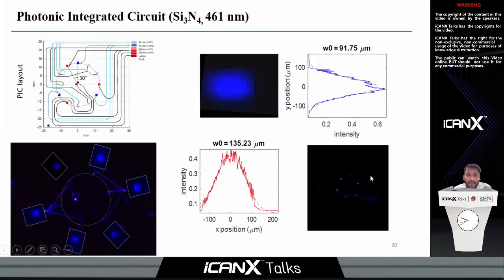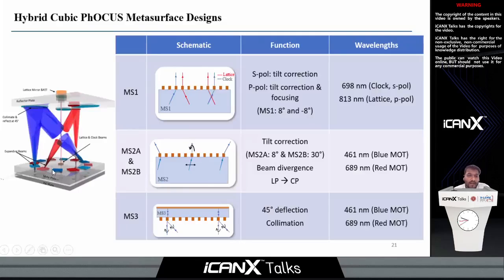So that magic is done using metasurfaces. I won't go through all the metasurface requirements in this project, but basically if I take one of these Lego blocks, let's say this blue one, and I look at it closely, then what this blue block metasurface is required to do is to take the linearly polarized 100 micron beam from the PIC and convert it to circularly polarized light, diverge it with quite high NA, and also change its directionality. So really this one Lego block is doing the job of 3 free space optics: a mirror, a lens, and a quarter wave plate at these 2 wavelengths. So it's quite remarkable, this multifunctional approach.